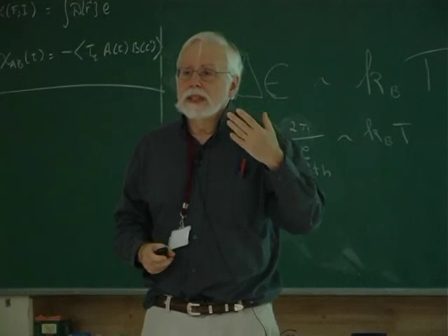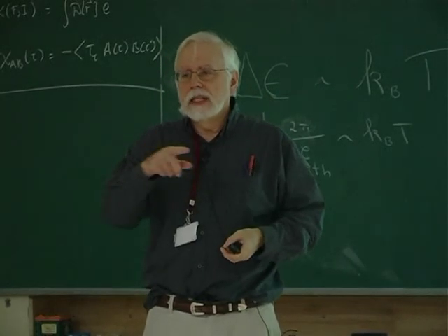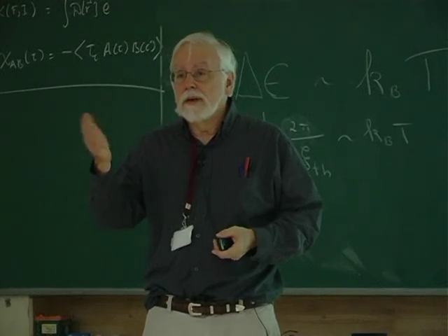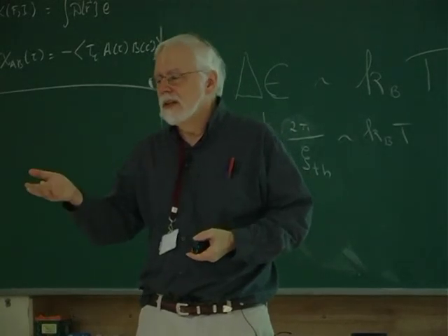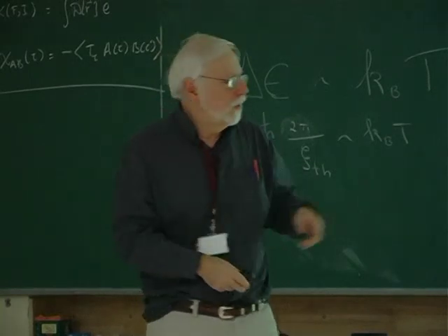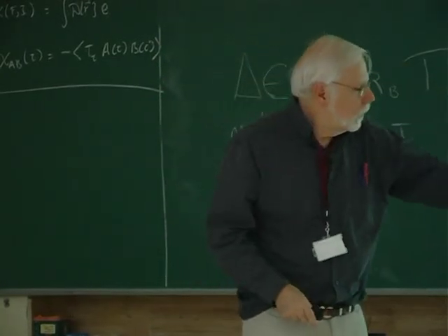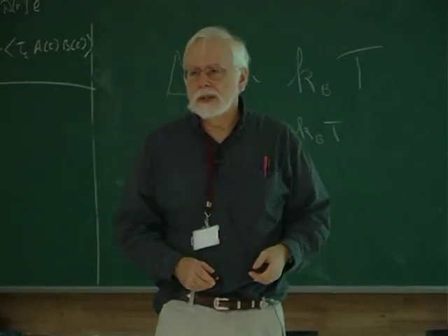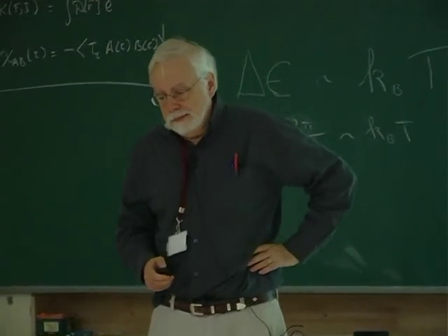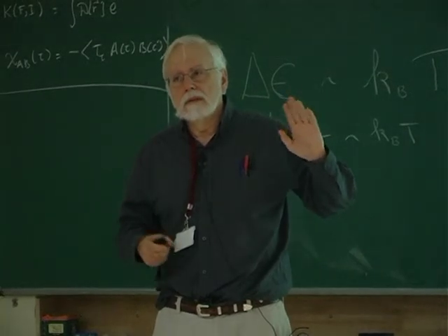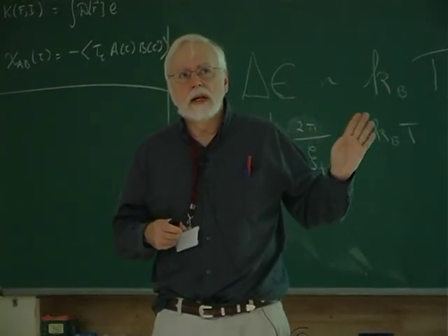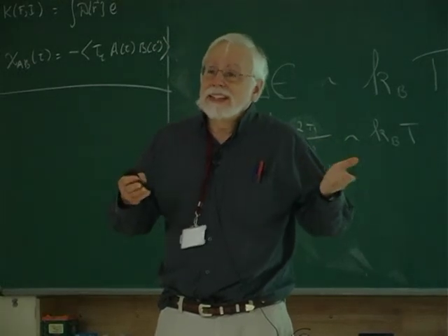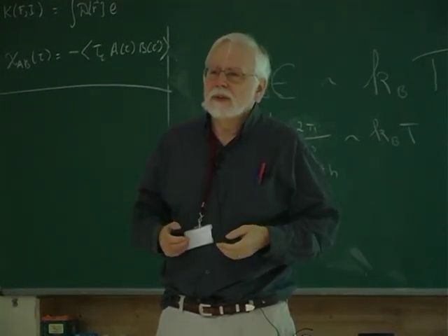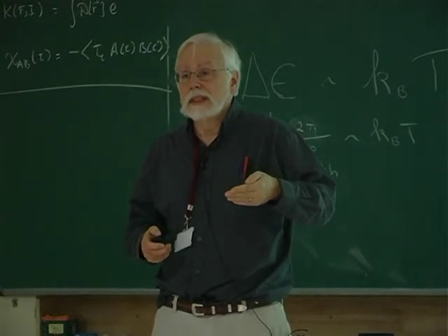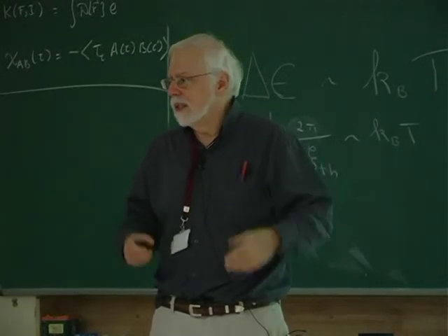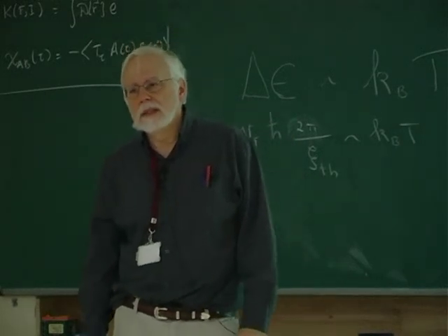So I don't have the numbers in my mind, but I've seen curves, even within ordinary BCS theory. You look at D wave and S wave, and there's a huge difference. The S wave will go like this, and the D wave will fall very quickly with disorder. But it turns out that anyway, the high temperature superconductors are surprisingly resilient to disorder. At the beginning, people were using this argument to say it's not D wave because we see that it resists disorder.